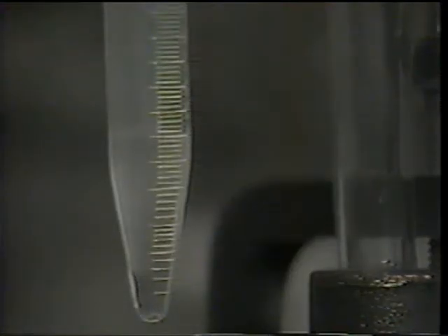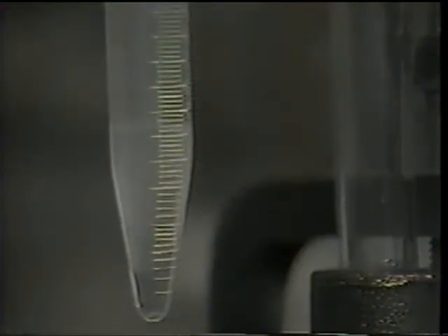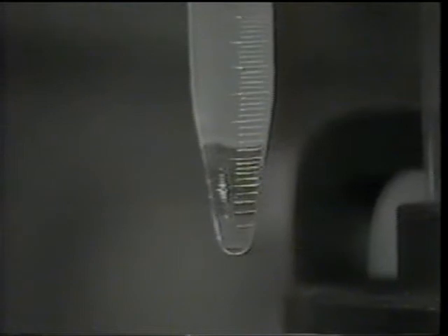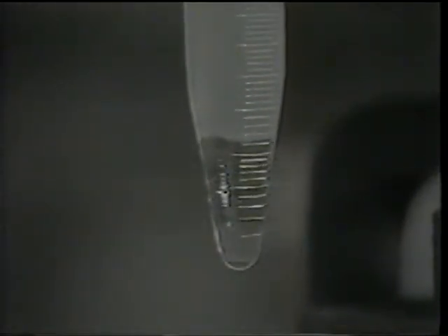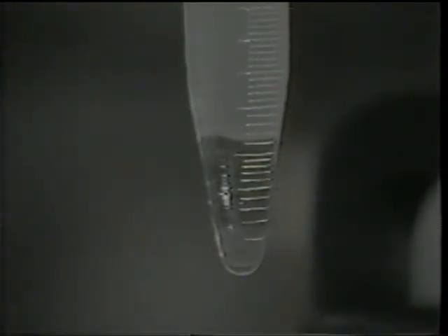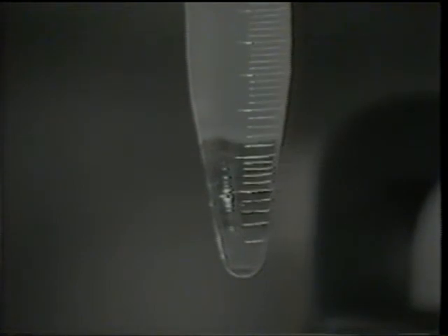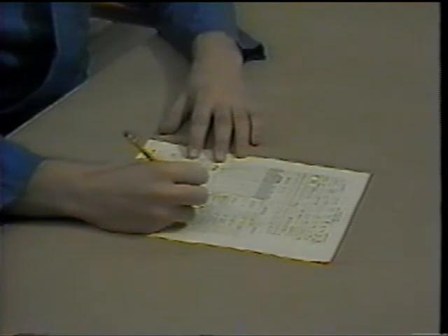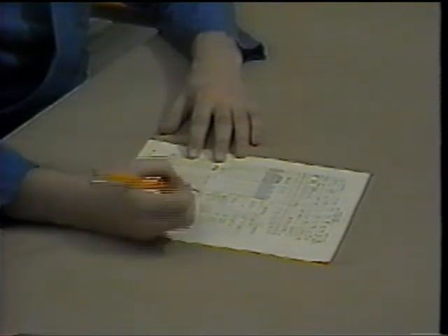Start distilling the mix and solvent by applying heat so that it begins to reflux within 5 to 10 minutes, and the solvent drips at a rate of about 85 to 95 drops per minute. But be careful in heating it so that the solvent does not ignite. Continue the distillation process until 3 consecutive readings at 15-minute intervals show no increase in moisture. From this reading and the weight of the sample, you can calculate the moisture content.